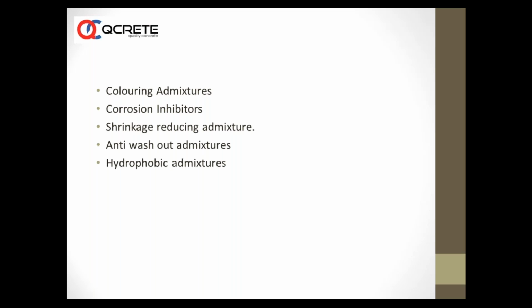We have anti-washout admixtures, used when you want to place concrete in water, close to marine structures or underwater, where you need something to bind the cement content, otherwise it will be washed off. These materials, based on cellulose and similar substances, hold the concrete in a thick, viscous state and prevent water from washing off the cement. Setting happens with slight delay, but that doesn't matter. These are special admixtures used for underwater works.